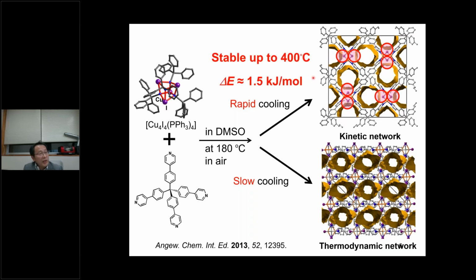Then we tested the stability of the network. Even as a kinetic structure, this network is stable enough up to 400 degrees. And we calculated the stabilization energy. The energy difference between the kinetic and thermodynamic network is just 1.5 kilojoules per mole. So even as a kinetic product, you can use this kind of kinetic MOF for application. Actually, using this one, we adsorbed iodine by chemisorption.